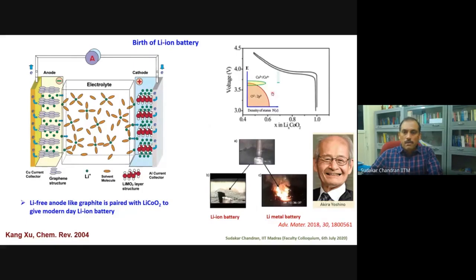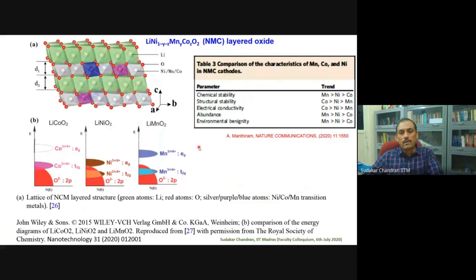This is again not a completely acceptable compound, for the reason that the lithium you could extract from this compound, LiCoO2, is only half. So you cannot remove the other half. The reason is that the cobalt redox energy levels overlap with the oxygen 2p bands. And therefore, if you try to extract more than half the lithium, you also tend to remove electrons from the 2p bands, which makes the oxygen escape from the lattice, and therefore the structure collapses. So despite its wonderful cathode properties, it could not be used to its fullest capacity. And the problem that exists till today is that there is no compound where you can extract one lithium equivalent, one lithium from the formula unit.